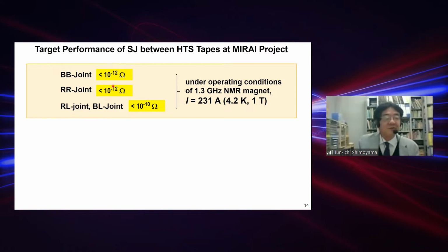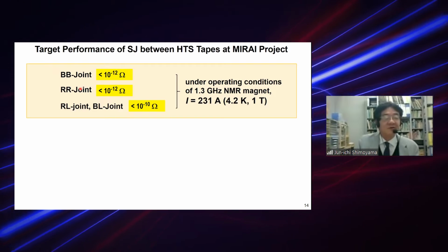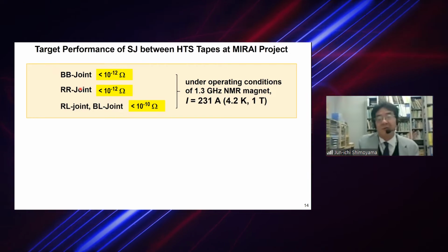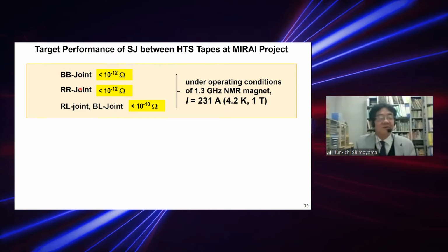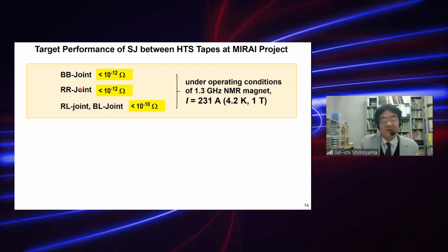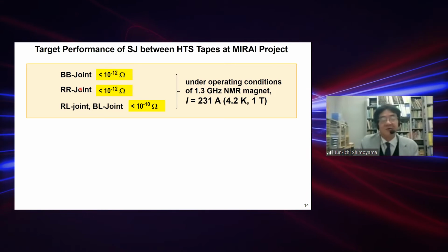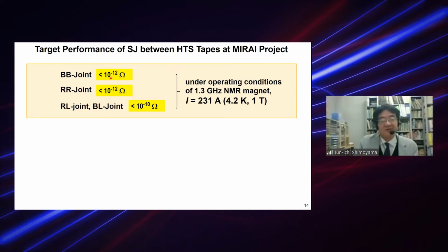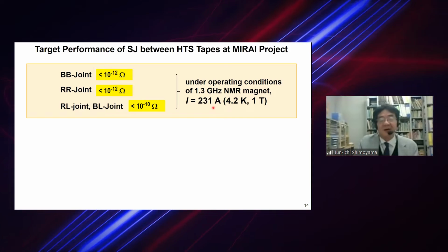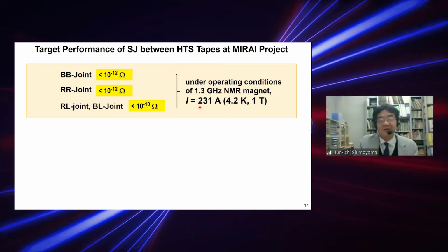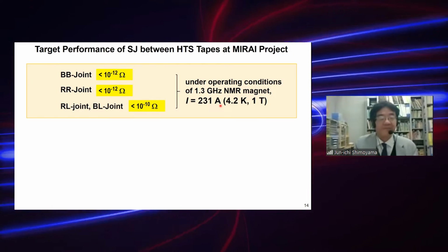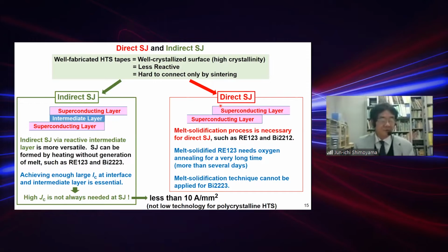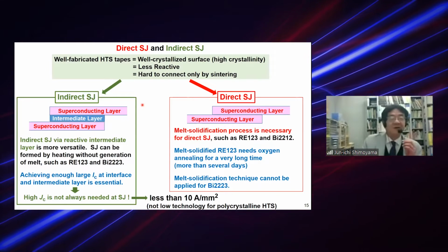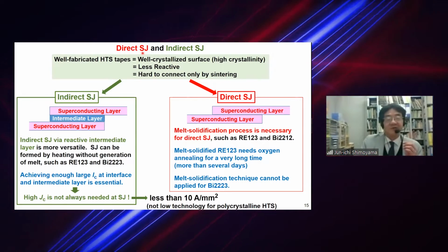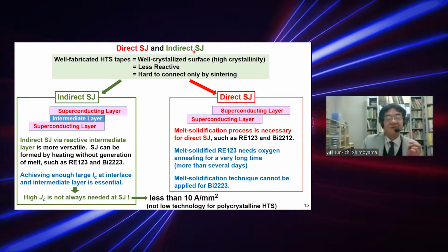As I told you, the BB joint and RR joint need very low joint resistance at 4.2 Kelvin in a field lower than 1 Tesla, that is 10 to the minus 12 ohms, applying a current of 231 amps. So let me think about the direct superconducting joint and indirect superconducting joint.